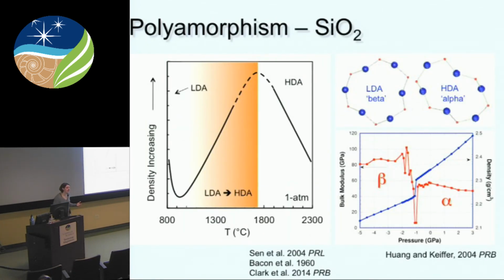Okay, at high temperatures, silicate melts at 1 atmosphere also have regions of increasing density. So normally, what we have here is density increasing that way as a function of temperature. And normally, as you heat up a material, thermal expansion leads to a lower density. And that's what you see here. But between about 900 and 1700 degrees C for silica, as you increase temperature, you actually increase density. And what we've shown is that this corresponds to the existence of 2 polyamorphic phases in silica. These are similar to the alpha-beta cristobalite transition. They're constructed of the same major units, predominantly 6-membered rings of silica, but we actually see a difference in the physical properties of the 2 phases, the bulk moduli and those sorts of things.